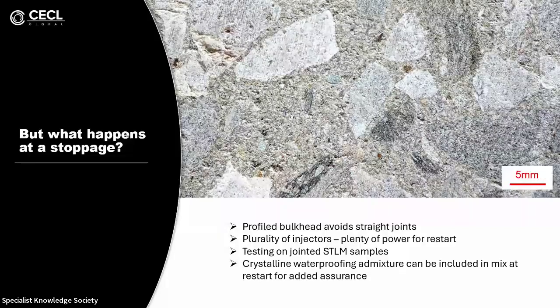I've had a few questions on what happens after stoppage and whether or not there'll be a cold joint in the past for this process. We all know that the inevitable happens in tunneling, and stoppages are part and parcel of that. So to answer this, we formed some samples in 2 halves: forming a half height sample, leaving it for 7 days, then coming back and forming a second half of the sample on top to create a joint in the sample. The high pressure in the process means that these joints are very tight and essentially invisible. Early water penetration tests have also indicated that these joints aren't forming any sort of preferential water path.